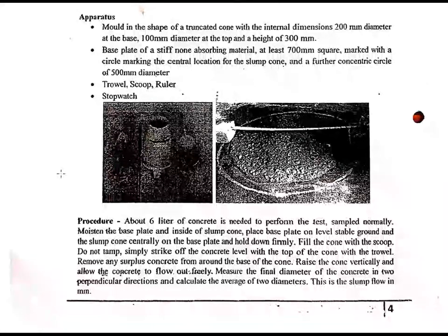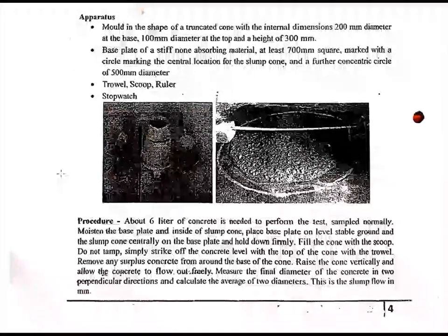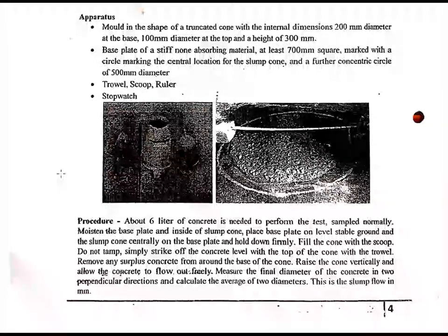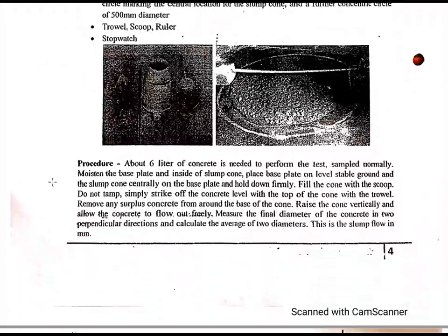So that time is noted, and then we have to measure the diameter of the spread. The concrete has spread, no? So that diameter we have to measure using a tape. We have to take the diameter in 2 to 3 directions. The average of it will give you the slump flow diameter.